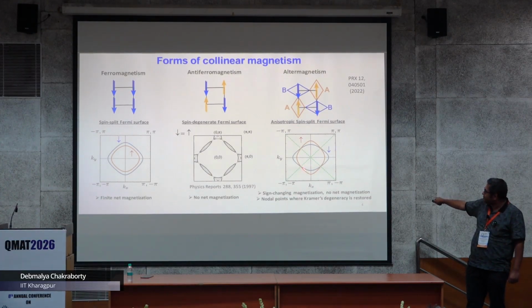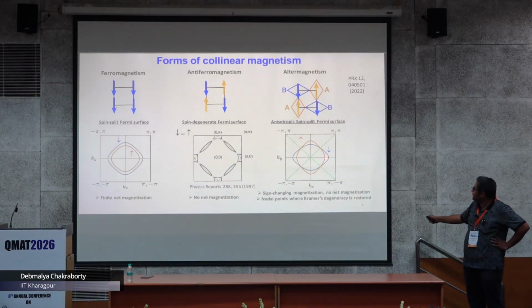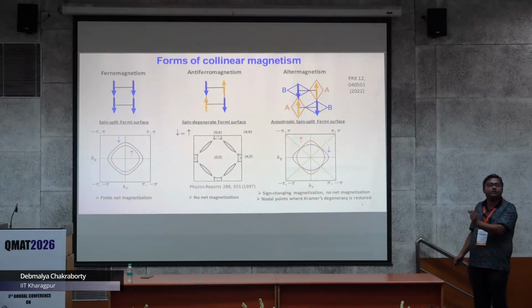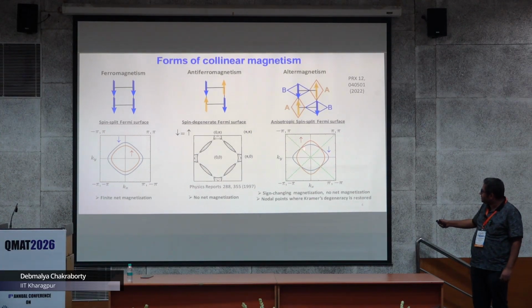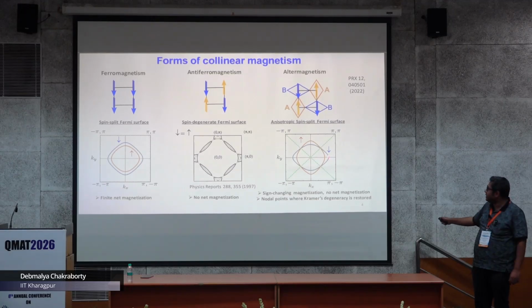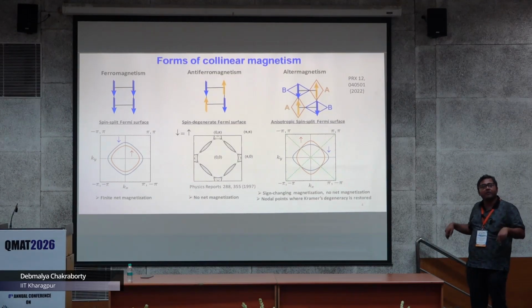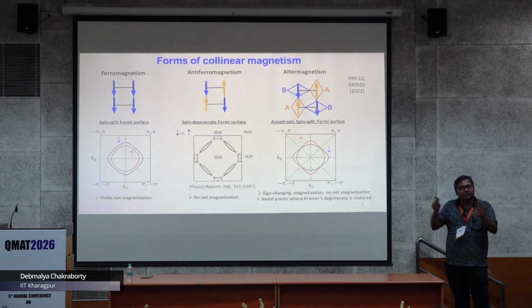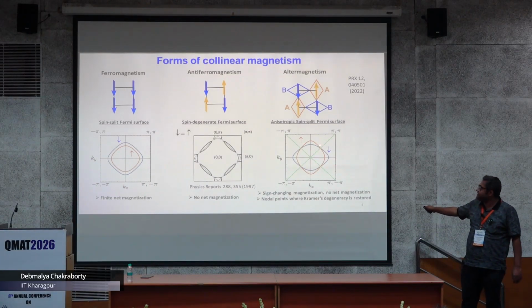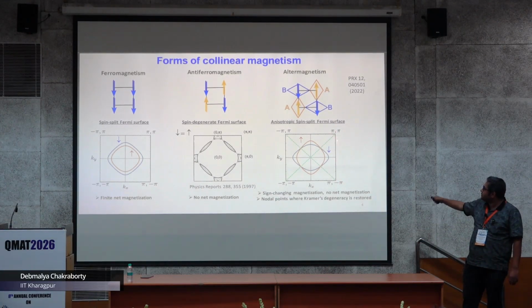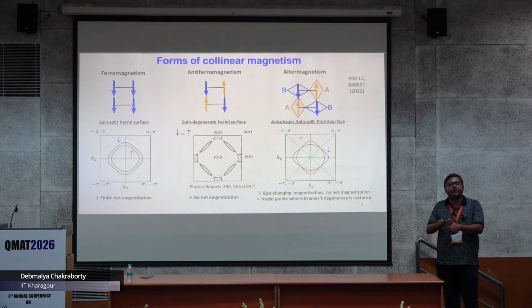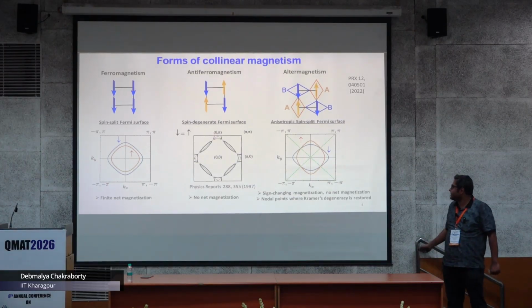So basically what happens, if you look at the Fermi surface, the yellow one, let's say the up spin, and the blue one, which is the down spin, will be split, and this splitting is the strength of the magnetization. And if you look at the magnetization throughout the Brillouin zone, it would be positive and negative. So the net magnetization will be 0. So there is no net magnetization in the system. It will be sign changing, and there are points, like these green dashed lines, which are like the nodal points where up and down are the same Fermi surface. That means they are degenerate.